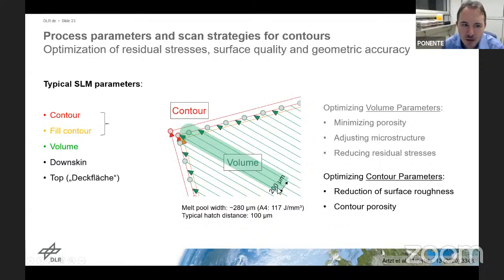In the contour region or surface region, things get complicated rather readily. You have these red contour lines, which you can have different numbers of, and in between the green volume, you have a fill contour shown here in yellow that overlaps those regions. And adjusting these overlaps, the distances, the parameters in between, gives you a large parameter space with possibility to optimize your surfaces, but it's also quite tedious, let's put it that way.